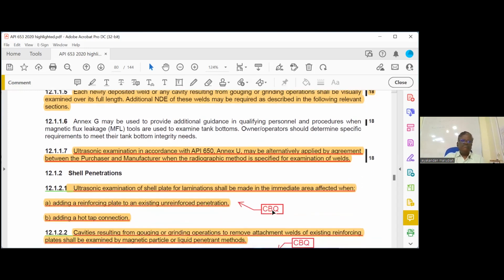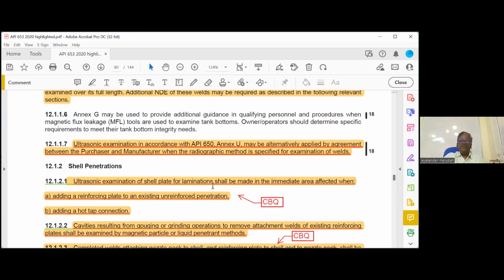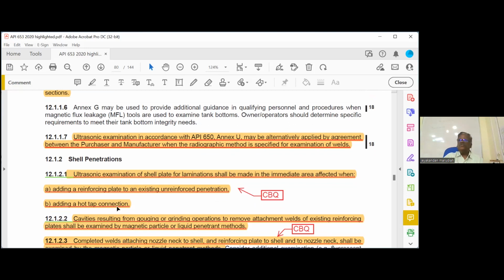Then coming to the shell penetrations. Now, where we have to do UT for lamination, very important. So UT for lamination check, not defect, we do before you cut any nozzle in a shell. In service, you have to do the lamination check. Or if you want to install a hot tap, that also we have to do the lamination check. Very, very important. Ultrasonic examination of shell plate for lamination shall be made in the immediate area when adding a reinforcement to an existing unreinforced penetration or adding a hot tap. Suppose you are putting a reinforcing plate, you have to check the lamination, and the hot tap location also you have to check. That is a closed book question.